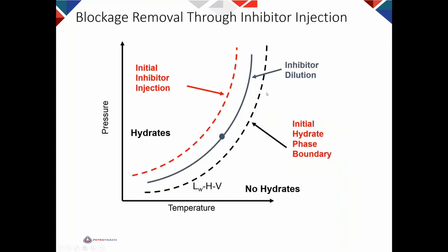So you see that this was the original hydrate phase boundary. This was the hydrate phase boundary when you inject inhibitor. Now the hydrate produces water that will dilute the inhibitor and hydrate melting will stop. So you need to inject more inhibitor. But at any point, you see that you need to provide heat. Whether it is with depressurization, whether it is with inhibitor injection, you provide the heat directly. You need to remember heat needs to be provided either directly or indirectly.